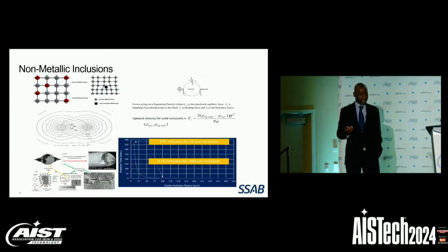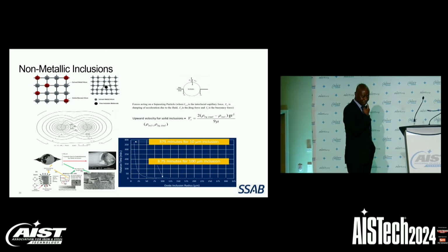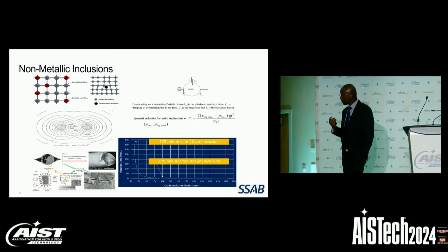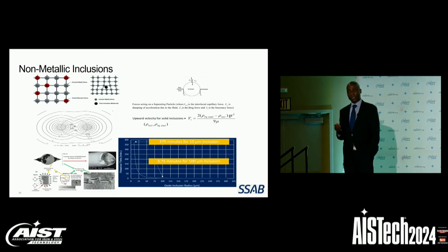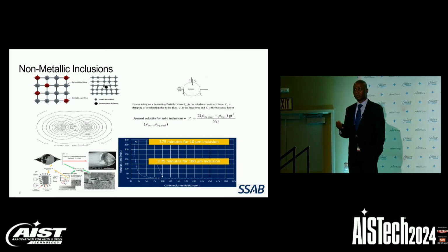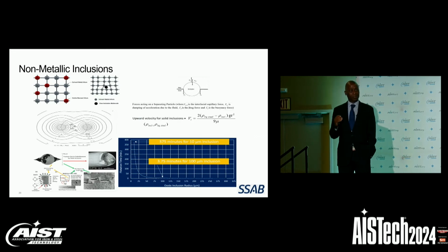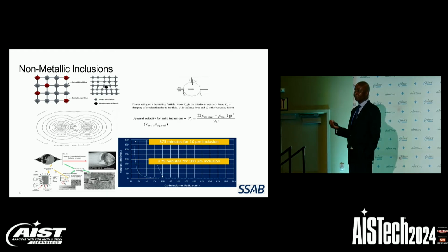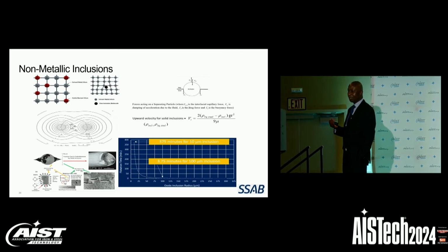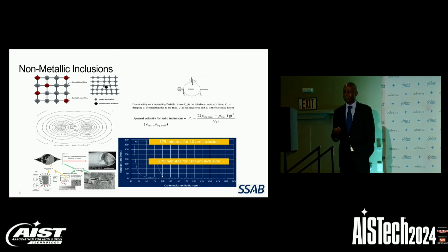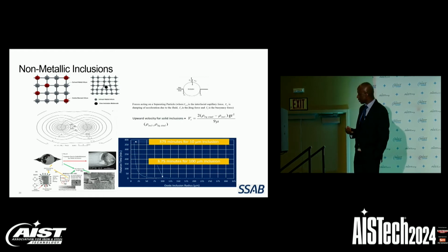So one of the tasks that the operators have to perform during refining at the ladle metallurgy station is to ensure that we reduce the population densities of non-metallic inclusions before they send the ladle to the caster for casting. Non-metallic inclusions can be very detrimental to the mechanical properties of steel because of the disparity between elastic and thermal properties of steel and non-metallic inclusions. So properties such as resistance to fatigue, toughness, and resistance to hydrogen-induced cracking can be degraded because of the presence of a significant amount of inclusions in the steel.